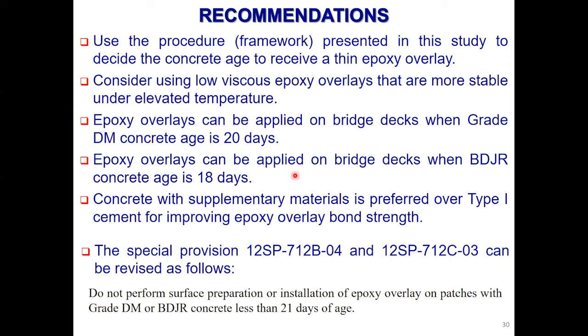And then by looking at all these right now, we can say you can apply this overlay after 21 days, because that will cover the cracking age, and still it is earlier than 28 days. So you will have a couple of days to finish all the work and open the bridge on day 28, instead of going a couple of days beyond the 28-day closure period. So this way we can save money and still get similar performance.